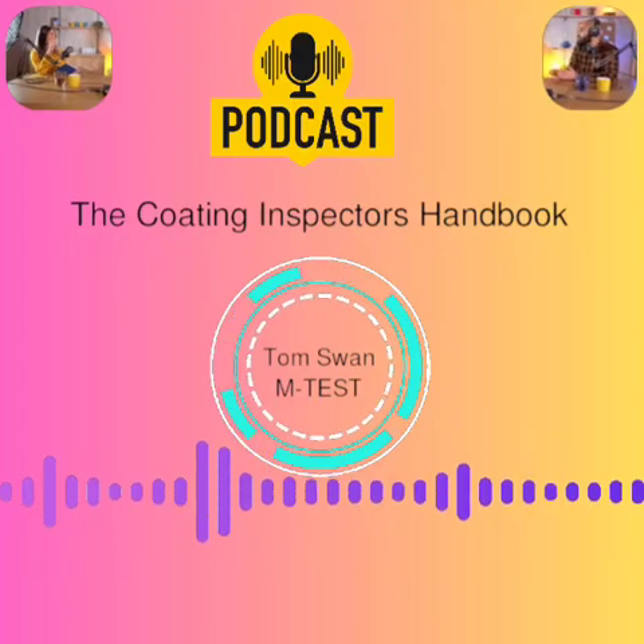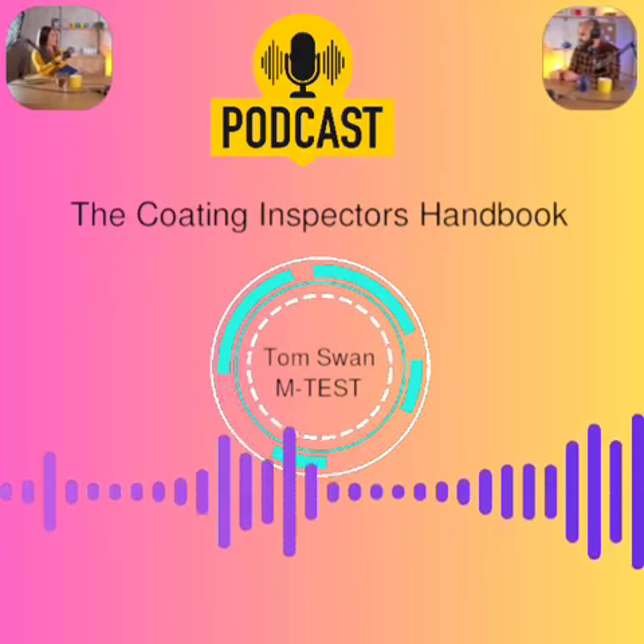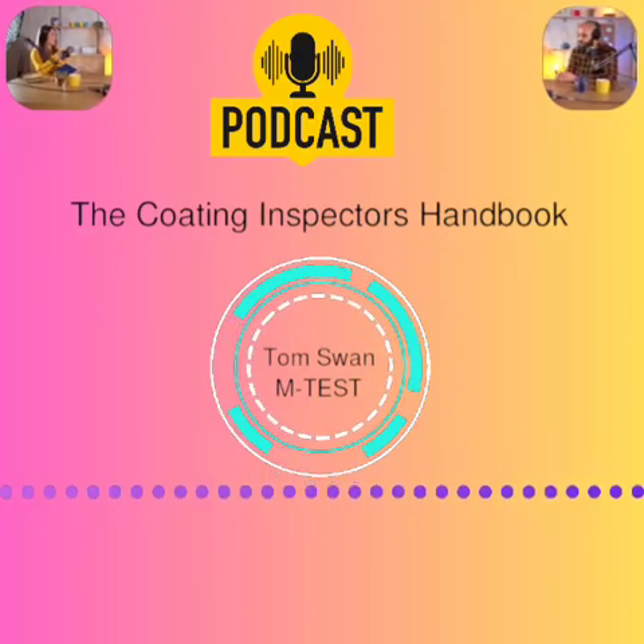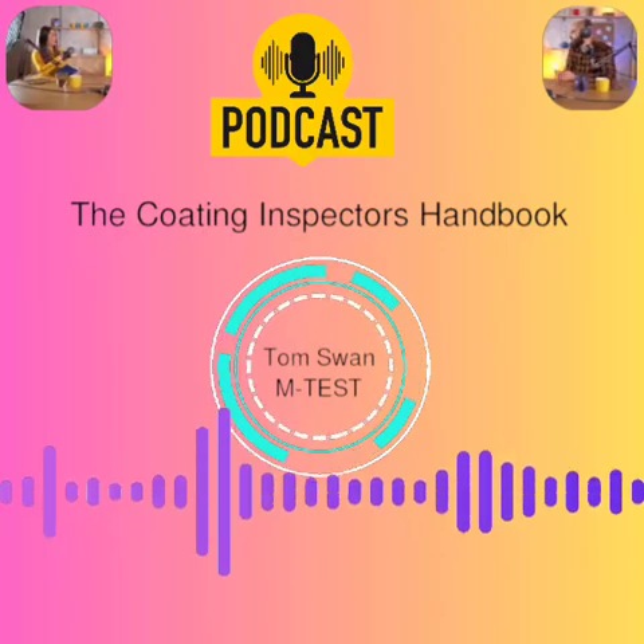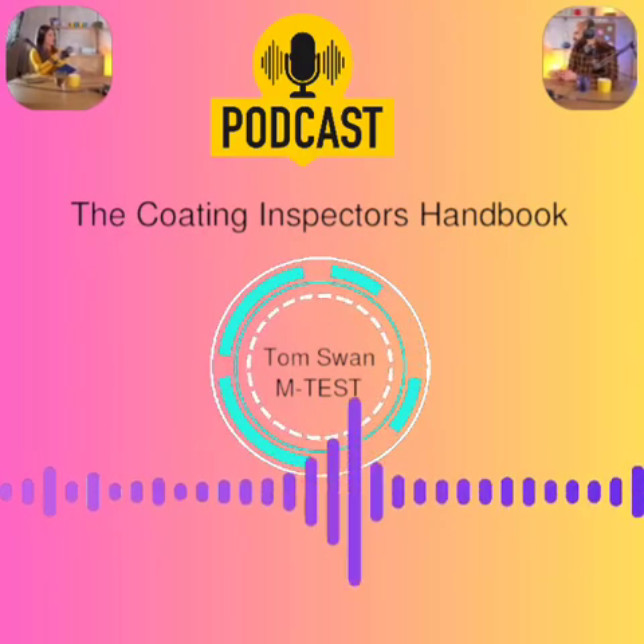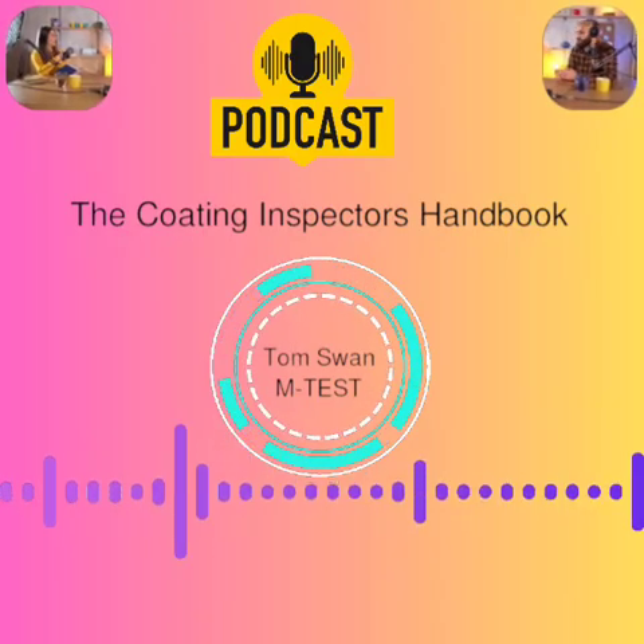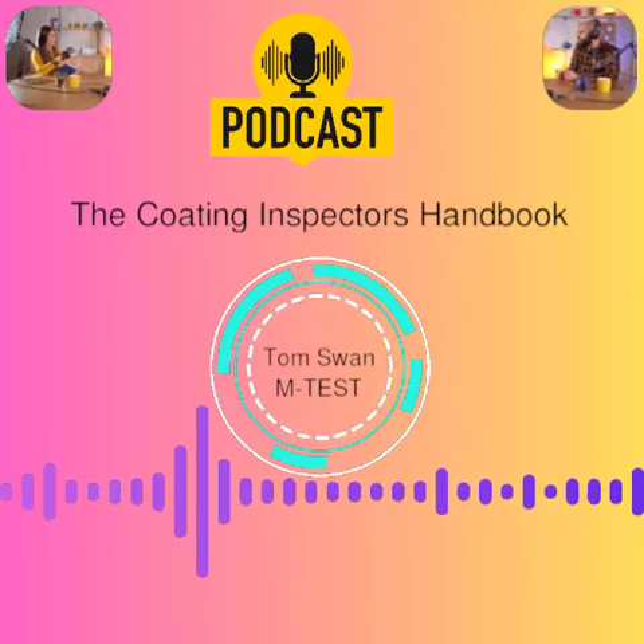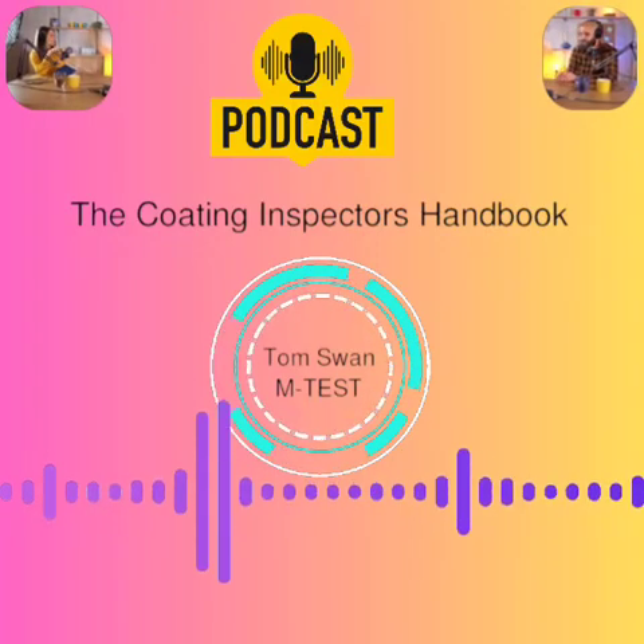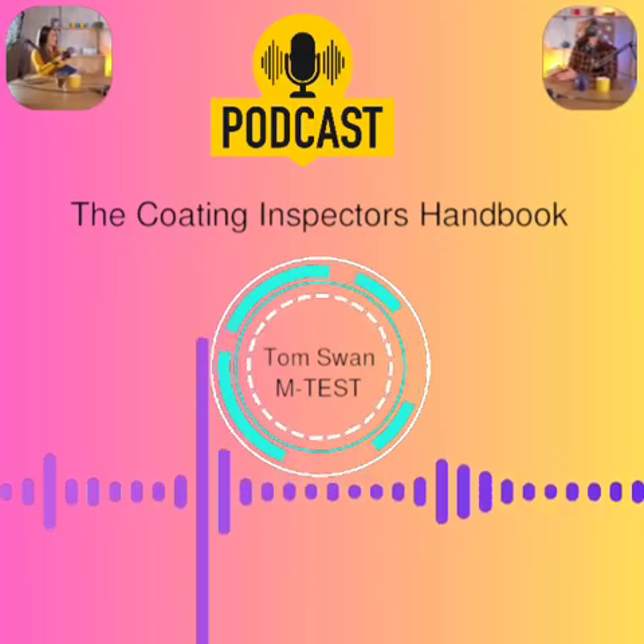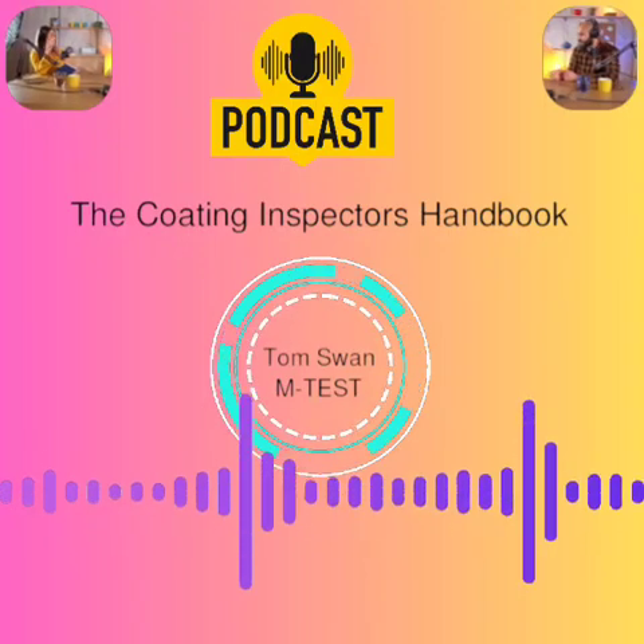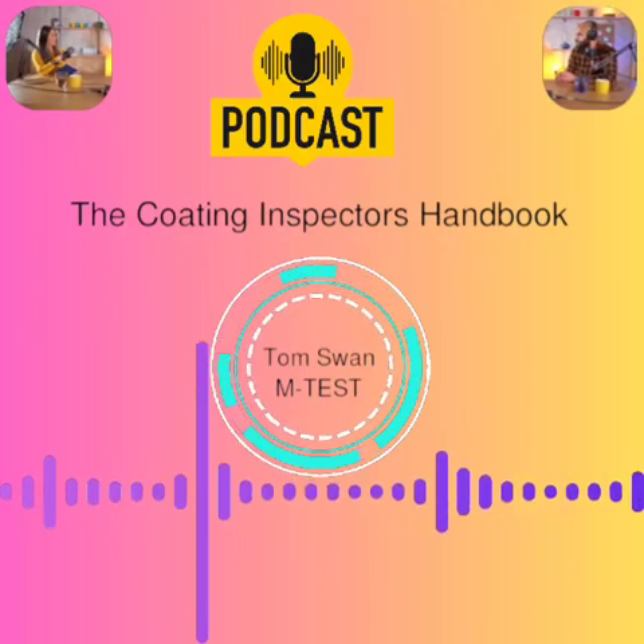Pull action matters. Manual versus auto. Rate. Squareness. Yes. Automatic testers, PATTI, Defelsko ATA, generally give higher, more consistent results than manual ones due to controlled pull rate. Slow, steady, even pull is best. Squareness is vital. Need a direct perpendicular pull, no twisting. Some testers self-align better than others. Misalignment causes peel failure, not true tensile.